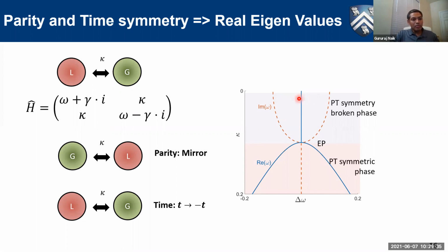This is extremely important for thermal emission, because I have the same resonant frequency but two modes. One has a very high imaginary value, which means it can take thermal photons from the vacuum fluctuations and then radiate out. And I have another one which has a very small imaginary part, which can take these thermal photons and store them, and then give very high selectivity, that is, high Q factors.